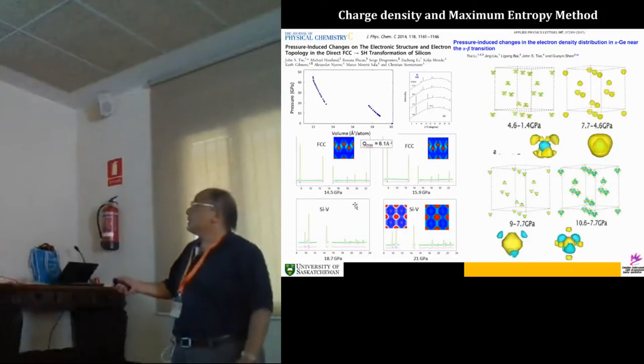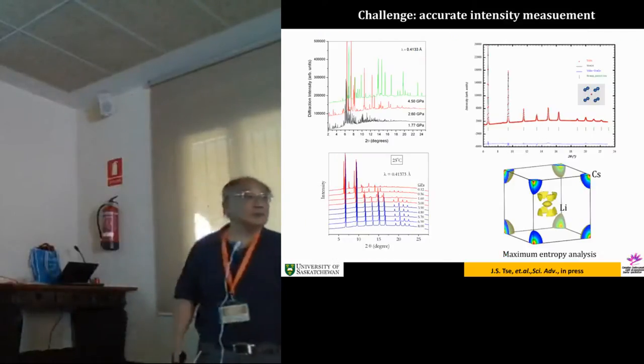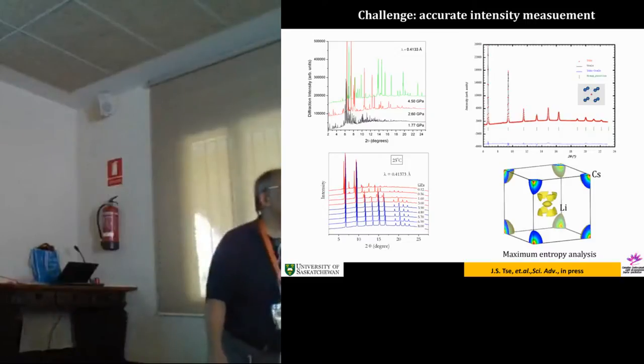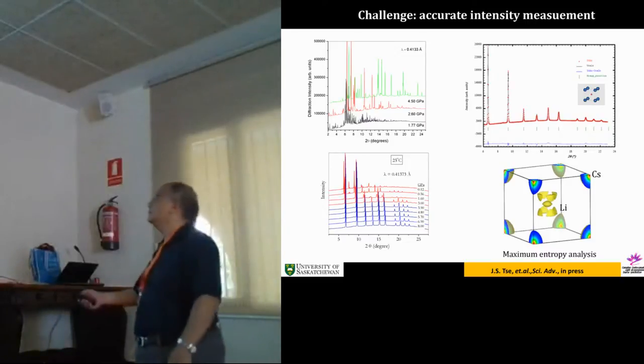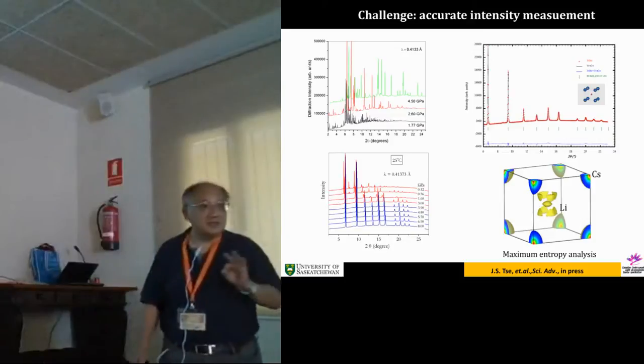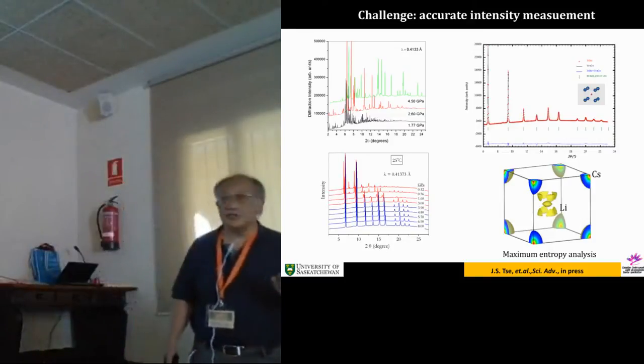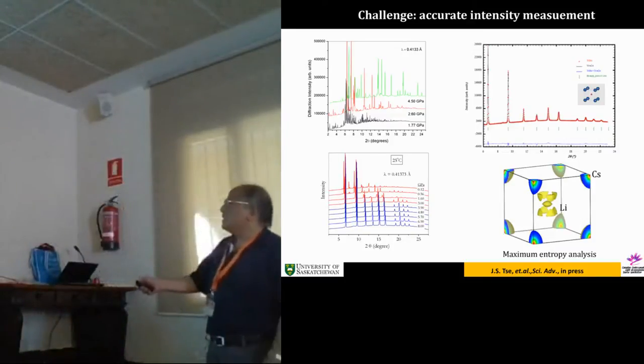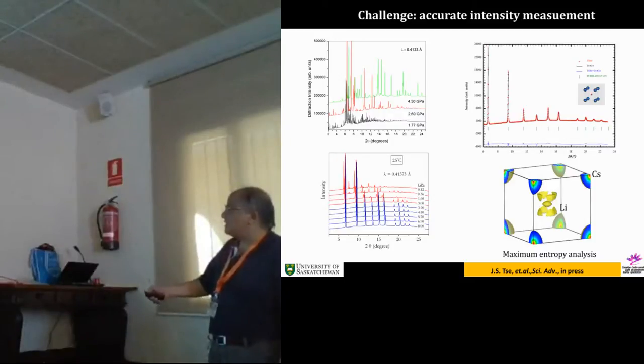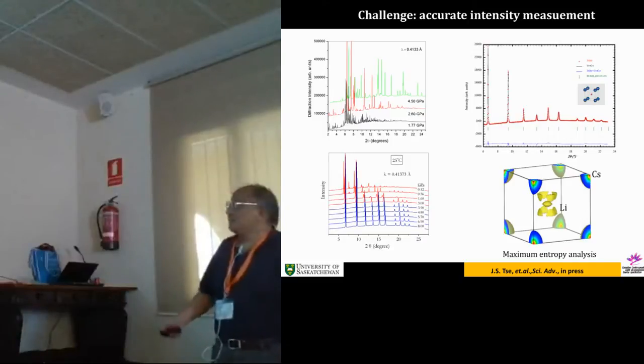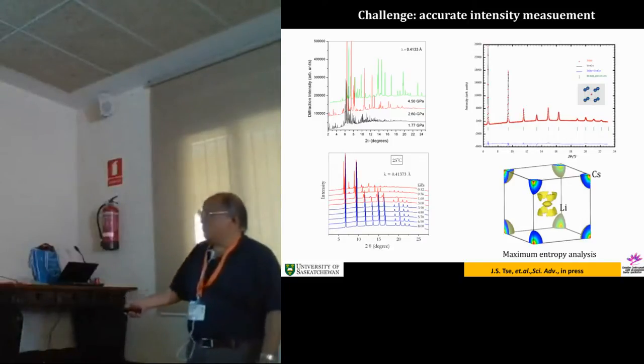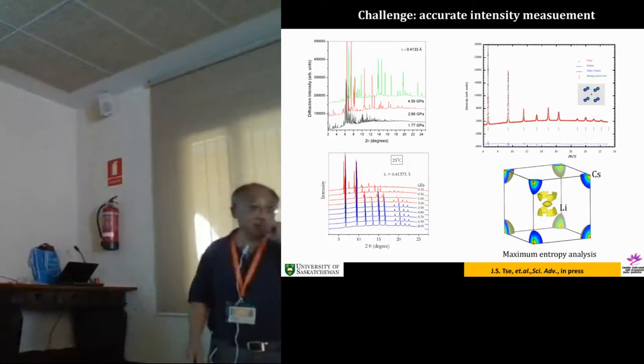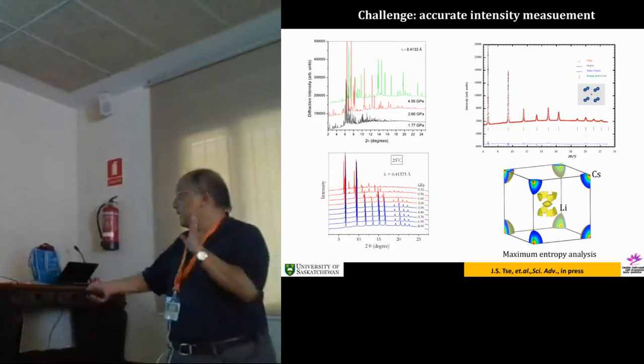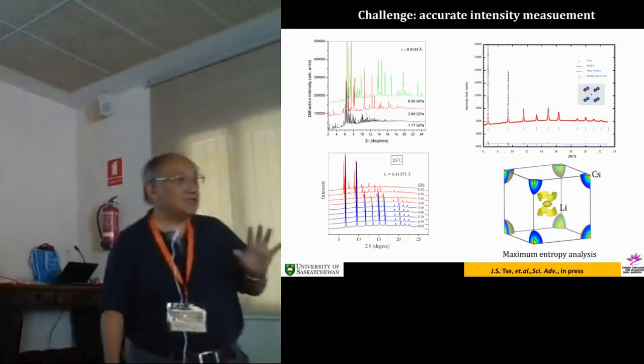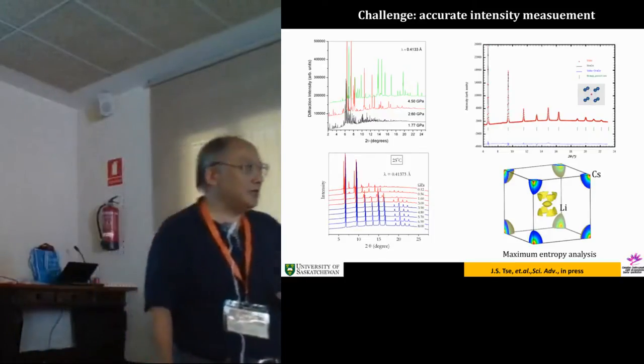So more recently, we took a piece of germanium, single crystal, and we did diffraction under high pressure. And they have the same transition at 11 GPa, from the FCC to the beta-tin structure. And we take the actual density difference between two pressure points. Here's 9 to 7, 10 to 7. I don't want to go into detail here. If you read the paper, this looks like a d orbital. So even at around 7 GPa, the d participation in the bonding is already important.